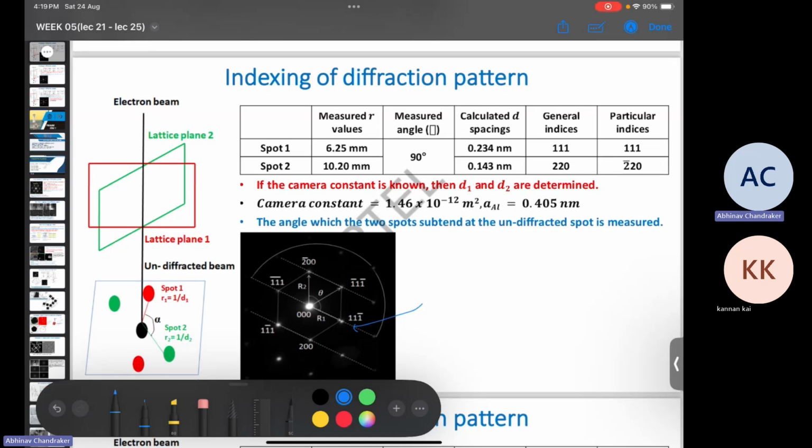So by understanding some of the theory of diffraction in TEM, we know that this spacing is 1 by small d, right? And also these all correspond to, or are scaled versions of, your diffraction vector g. So this is a scaled version of the 200 g vector, 2 bar 00 g vector, and so on.